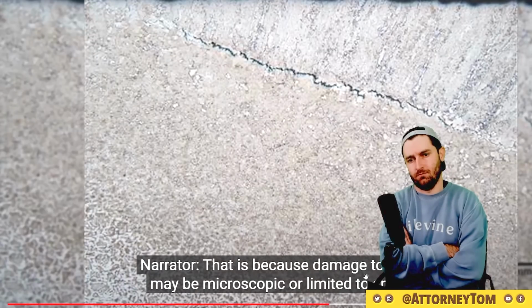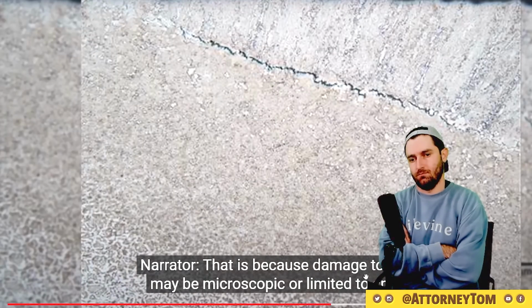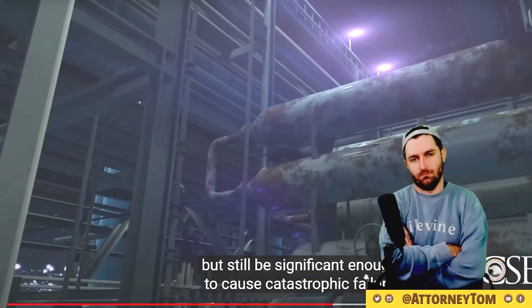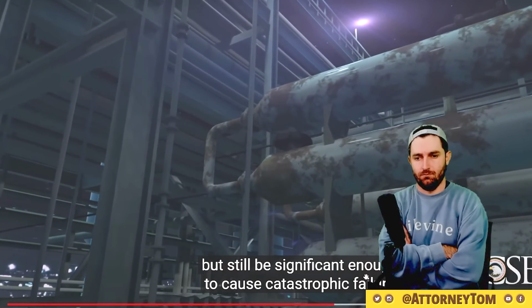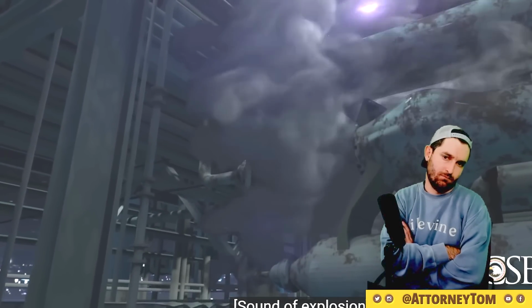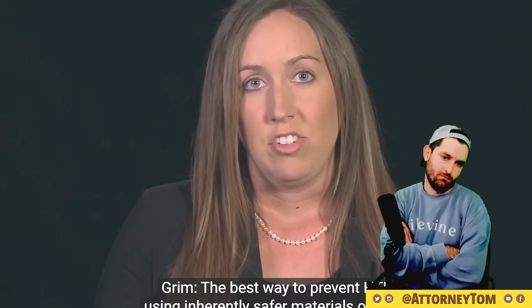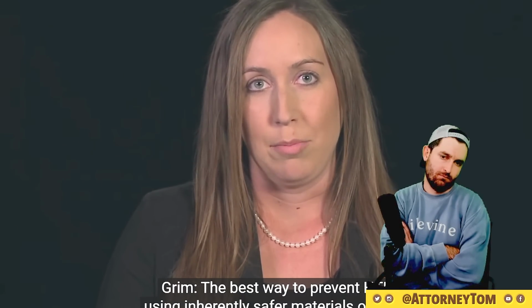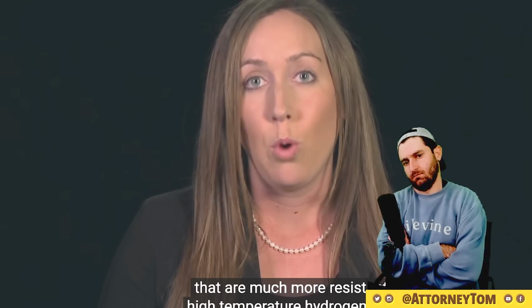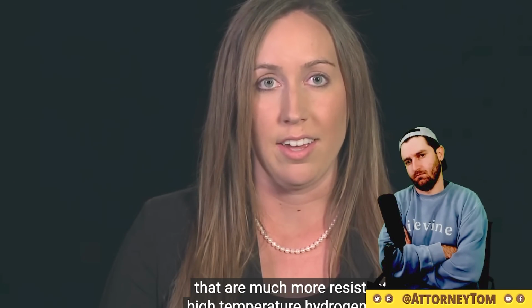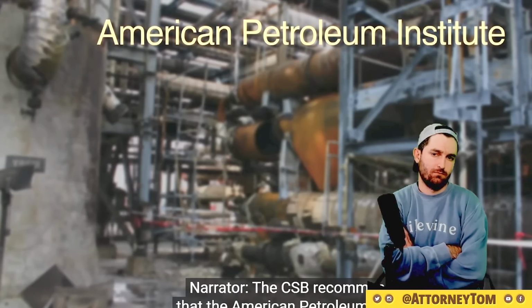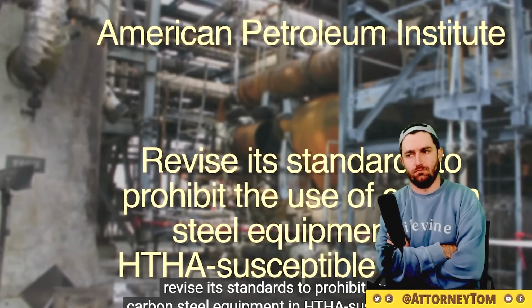That is because damage to equipment may be microscopic or limited to small areas, but still be significant enough to cause catastrophic failure. The best way to prevent HTHA is by using inherently safer materials of construction that are much more resistant to high-temperature hydrogen attack. The CSB recommended that the American Petroleum Institute revise its standards to prohibit the use of carbon steel equipment in HTHA susceptible service and to require verification of actual operating conditions.